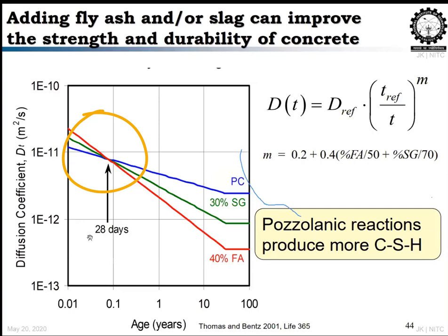You will say that there is no effect of using secondary cementitious material. Why do we have to use fly ash, slag, or some other cementitious material? But if you see, with the increase in age, 40% use of fly ash is changing the diffusion coefficient by almost 1 order, compared to the case in blue color, that is the Portland cement, which is nowhere comparable. That's why it is very, very important to use secondary cementitious material.